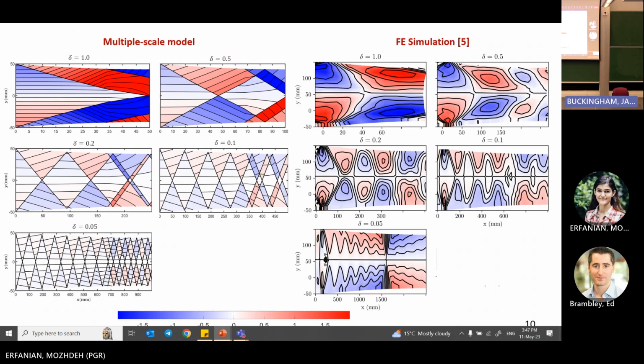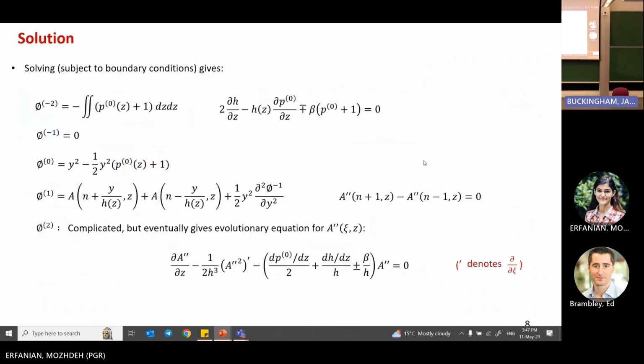So if I go back to these equations, I noted that the n and y dependency comes from the boundary condition, and we chose the simplest boundary condition to get a linear function for A. But if we include elasticity, then it wouldn't be linear, and then we need to solve this equation numerically. And the difficulty is that we have a discontinuity, a shock wave in the boundary condition, and therefore we need to carefully track the speed and also the amount of shock.